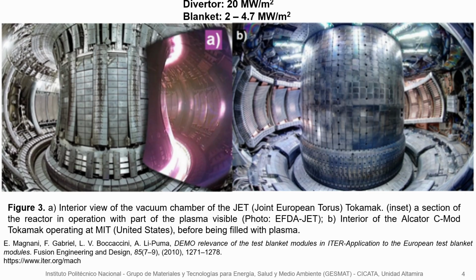This is achieved by inducing an electromagnetic current by means of coils coupled around the toroid, which also removes the electrons from the hydrogen isotopes, leaving them with a positive charge, which allows the fuel to be magnetically confined to the central region of the fuel vessel, away from the wall. This is because there is no material that can withstand the temperature at which the thermonuclear plasma begins to fuse. And that's why the material selected to be the armor in the first wall of the fuel vessels in nuclear fusion reactors is tungsten,